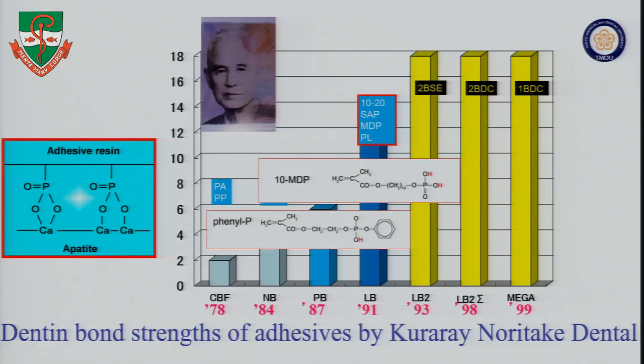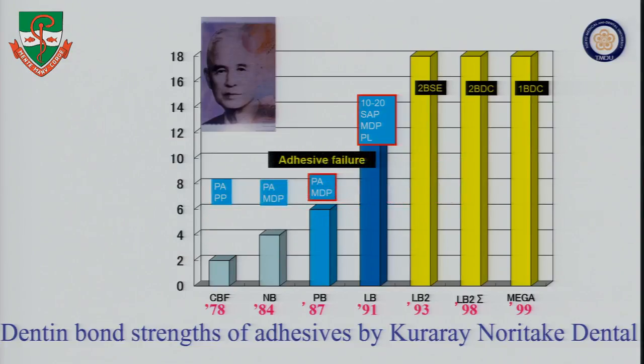At that time, people expected to have this kind of chemical reaction with hydroxyapatite, but unfortunately, at that time, there was no facility to analyze this kind of reaction. And after the light curing catalyst was developed, again, the bond strength became very high. And also, by the application of the primer, the bond strength became so high. However, these materials show the fracture at the bond interface between resin and dentin when we test it. But after the development of the self-etching materials, almost all of the specimens show cohesive failure in dentin when we test the bond strength.